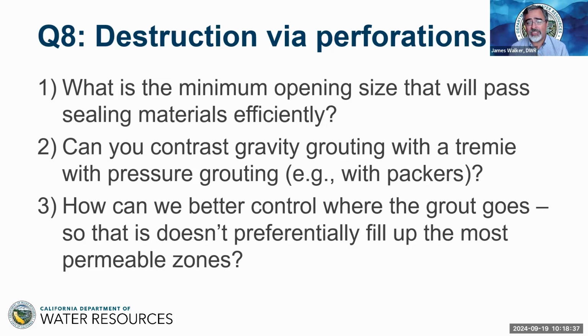First, our team could not find a basis for some of the rules of thumb for minimum perforation sizes to pass cement, such as for Mills knife cuts. ASTM D5299 recommends 4 rows of perforations, several millimeters long, and 15 perforations per linear meter, but provides no reference as to why. So we asked you to weigh in, noting that the Mills knife perforations are about 3/8 of an inch wide, shot perforations are 0.3 to 0.88 inches in diameter, and the smallest off-the-shelf monitoring well screen openings are 0.01 inches, and cathodic protection well vent openings are typically 0.01 to 0.02 inches, but can be as small as 0.006 inches if cut with a laser.